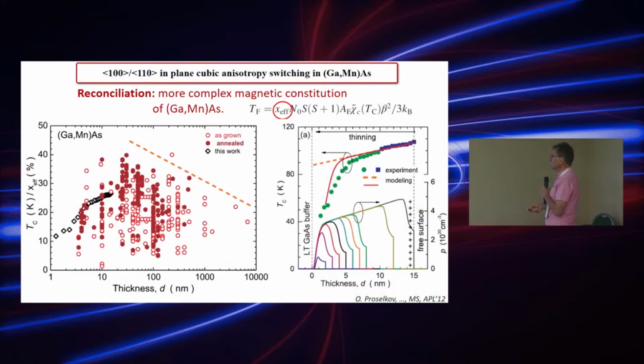that on this graph we collect the Curie temperature taken from many papers, about 75 papers, plotted as a function of the thickness of the layer. There has been a general trend seen that the Curie temperature was getting higher and higher as the layer thickness was getting thinner and thinner. However, let's say below some 15 nanometers, something strange happened because the Curie temperature was going down.